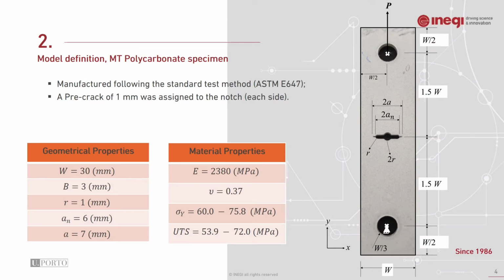So the model definition: the middle tension polycarbonate specimen has been prepared based on the ASTM standard, and afterwards it was pre-cracked by 1 millimeter on the notch on both sides. The geometrical properties, as can be seen, are W 30 millimeter, the thickness is 3 millimeter, the radius of the hole is 1 millimeter, the initial notch a_n is 6 millimeter, and the crack length is 7 millimeter. The material properties have been taken from the literature: Young's modulus, Poisson ratio, yield stress, and also ultimate tensile strength.